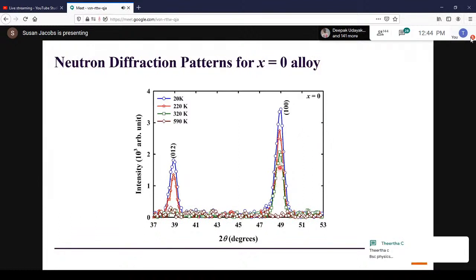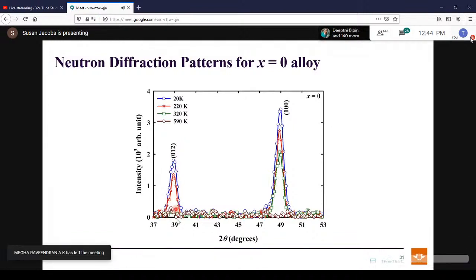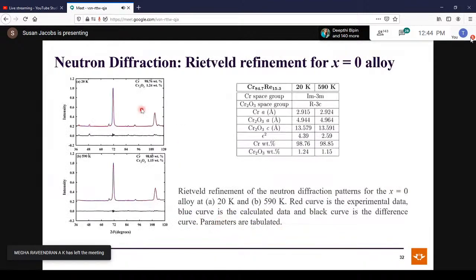Now, in addition to this peak, we see another peak at about 38 degrees. And when we did Rietveld refinement, we saw that it is actually chromium oxide. So now the presence of chromium oxide is confirmed in our system. This peak corresponds to Cr2O3, but it is present in very small quantities, at about 1.2 weight percent in all the alloys, but it is there. And we can extract other parameters from refinement.